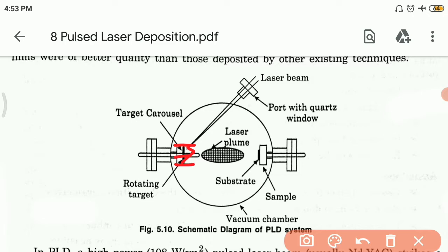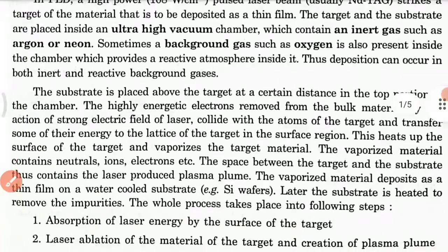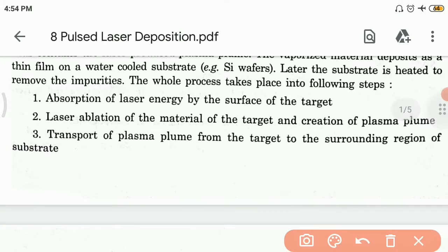The vaporized material contains neutrals, ions, electrons, etc., and the space between the target and substrate contains the laser produced plasma plume, where plume means vapor. The vaporized material deposits as a thin film on a water cooled substrate, for example silicon wafers. Later the substrate is heated up in order to remove impurities. The whole process of this PLD technique can be described in the following steps. Number one, absorption of laser energy by the surface of the target, then laser ablation of the material of the target and creation of the plasma plume.